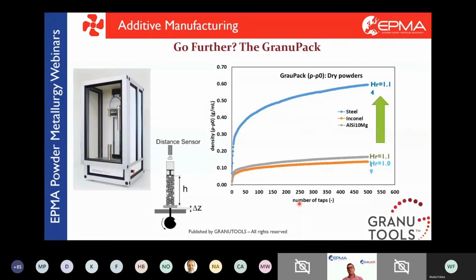One way to characterize the density of the powder bed is with the GranuPack, which is one of our instruments that measures the compaction dynamics. This is based on the number of taps - we're doing tap density, and we measure the compaction dynamics of the powder.